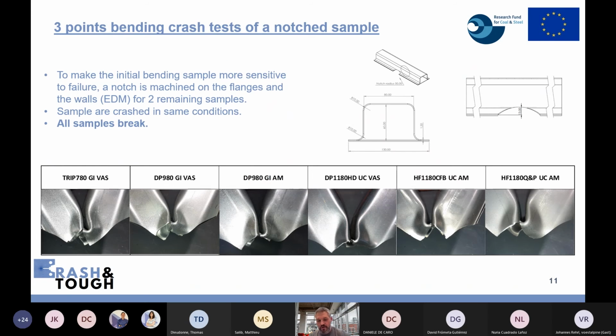That's why we wanted to modify the sample. We just machined a notch, as we can see here on the drawings, in order to make a weak point on the section and to reach some failure. And in these very severe conditions, all the samples failed. We can see here that actually the displacement is in high excess, and the sample should have failed quite early.